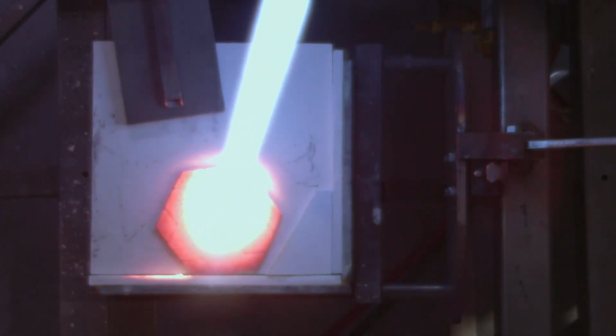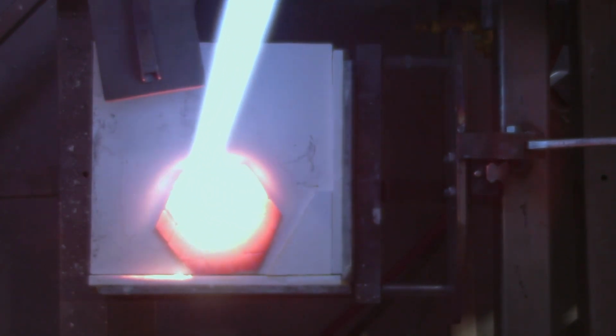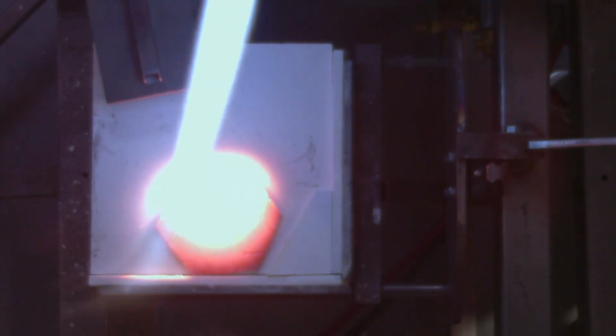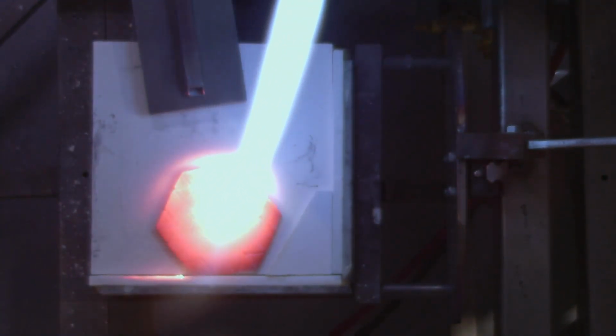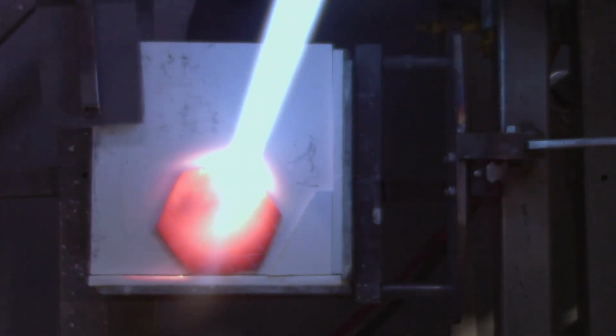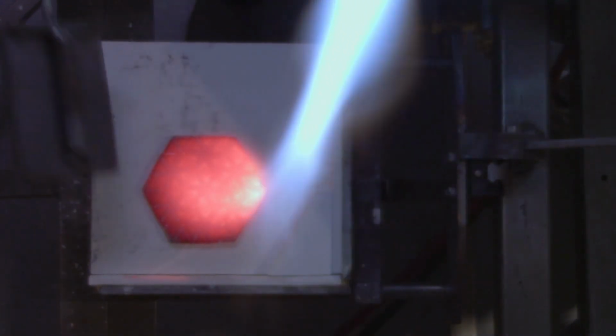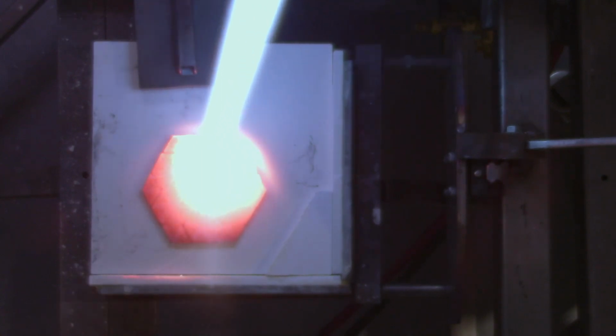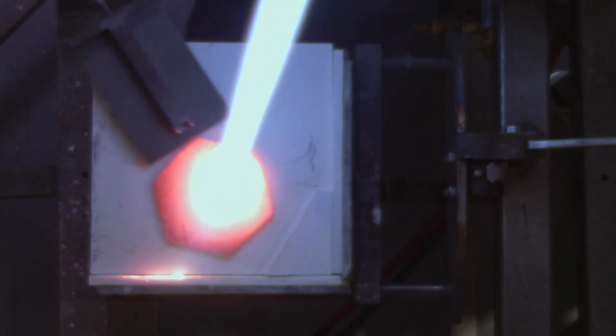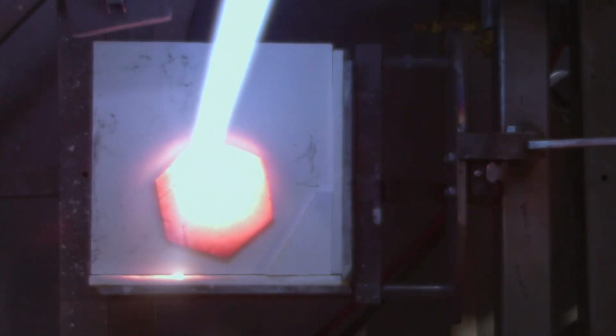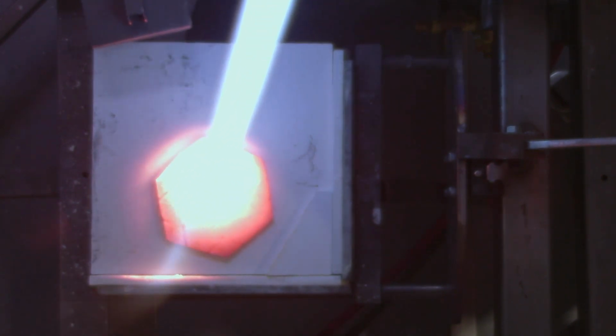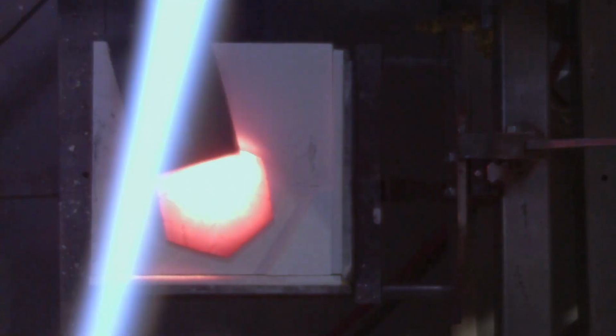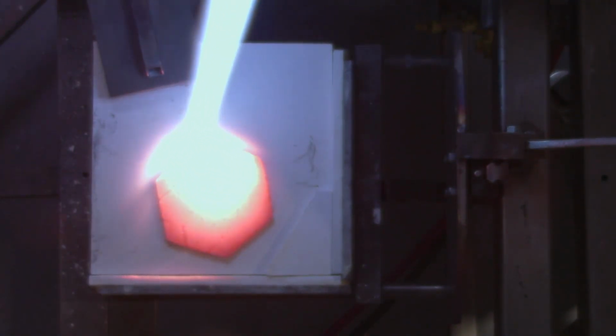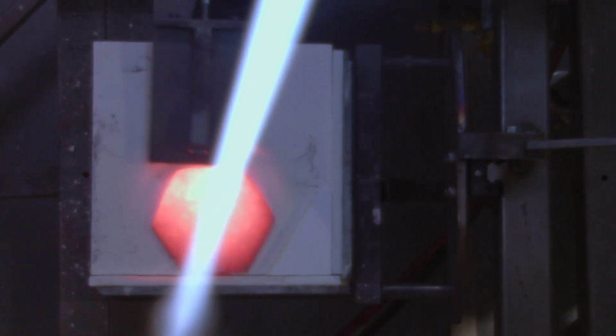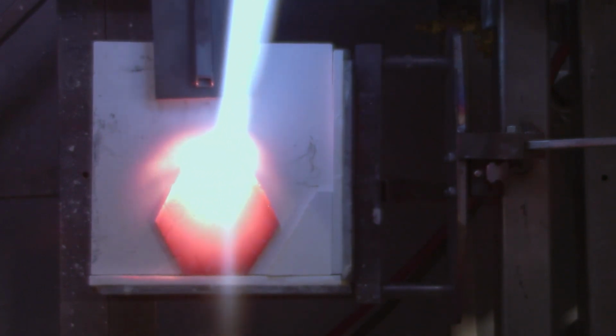The center is always the easiest to get fully melted together. The edges are always the more difficult part. The outer edges are by far the most difficult. Right along the outer edge, this is the part that's very, very hard to get melted together, because when I'm trying to get the torch flame on it, the outer edge is exposed to the air, and I'm overheating my ceramic plate, causing it to degrade a little bit more.